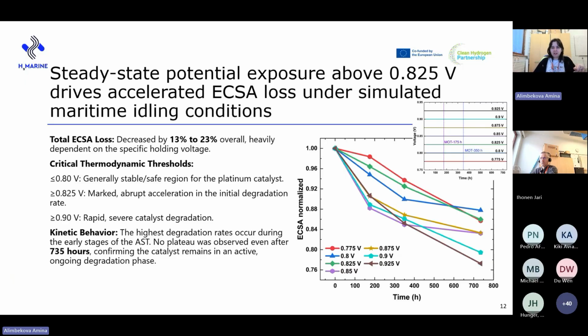Another finding that we can see from here is that long-term kinetic trend. So after 735 hours of exposure, the electrochemical surface area curves do not reach a plateau, suggesting that it's in the early to intermediate stage of its degradation.